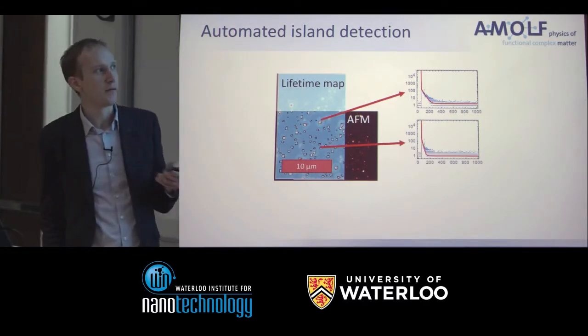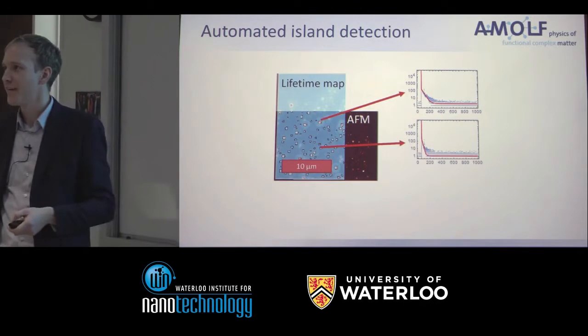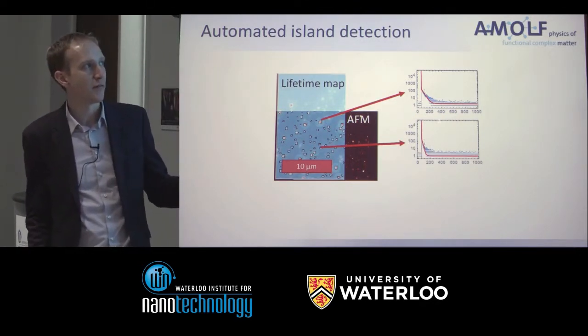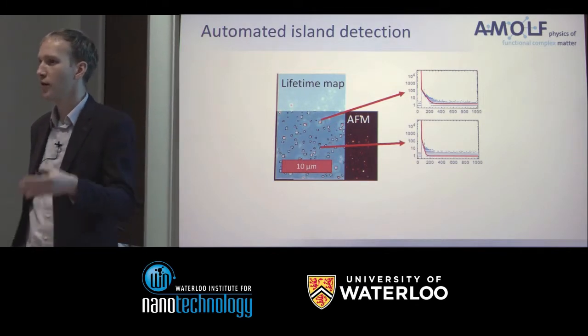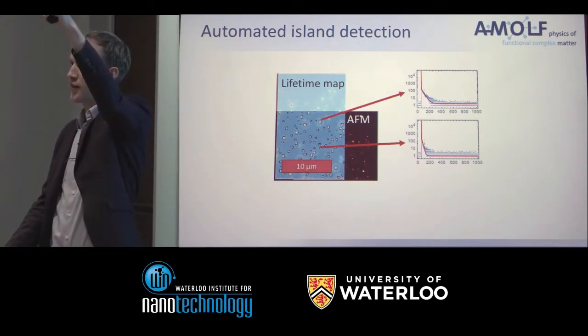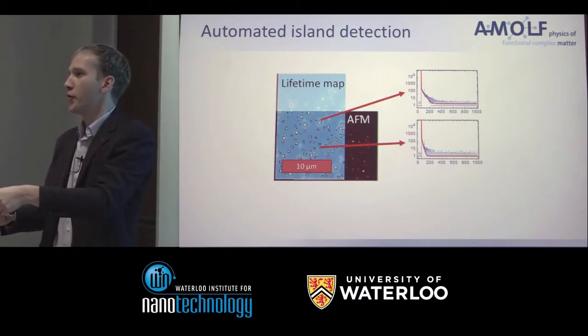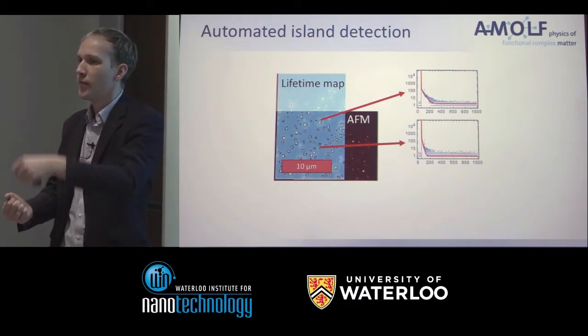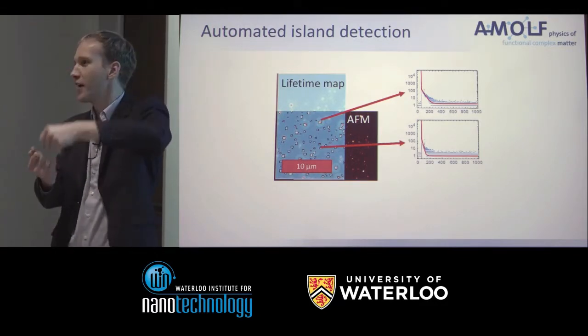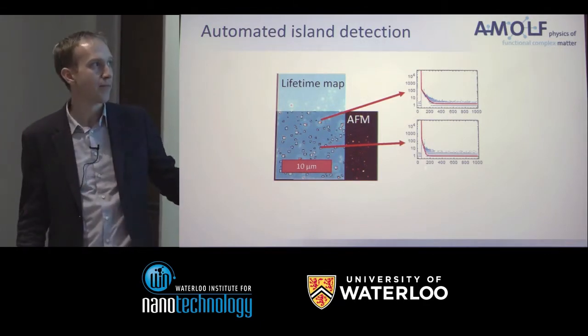So you're asking what indicates transfer if your lifetime becomes faster or slower. So we have these two lifetimes. Always when we measure these inefficient materials, you get two lifetimes. One is faster and one is slower. And that's because you first make your high energy exciton, and that can directly decay and emit a photon. And then this is the fast lifetime. Or you can first make these two triplet excitons, which can't decay by emitting a photon, but they can go back to a singlet exciton and then decay. So that's the delayed lifetime.